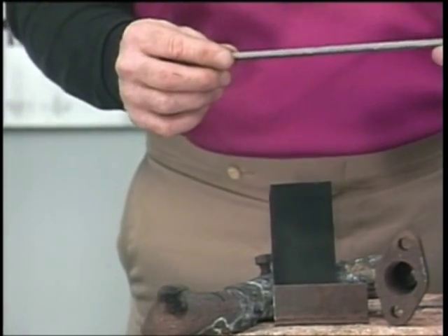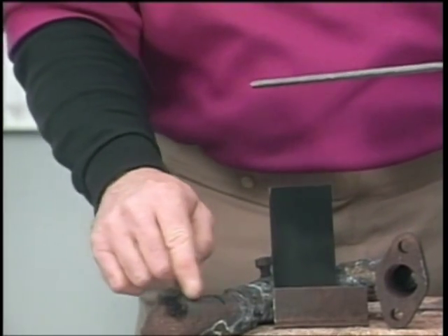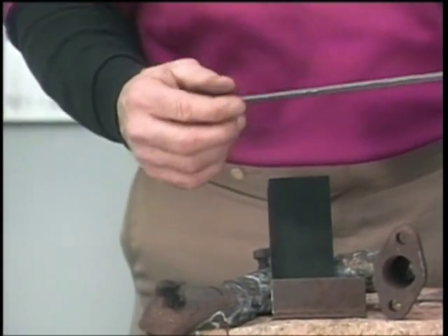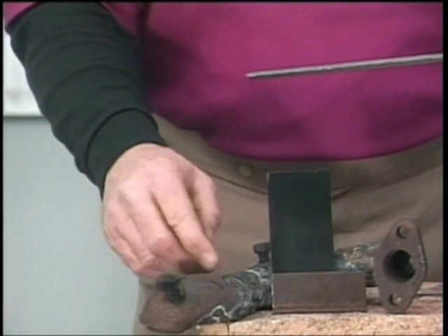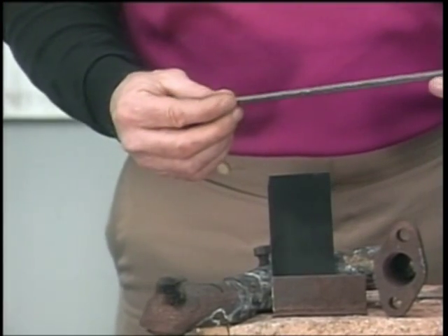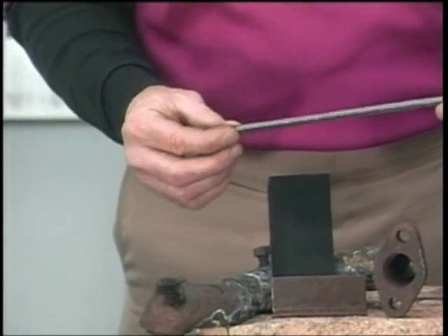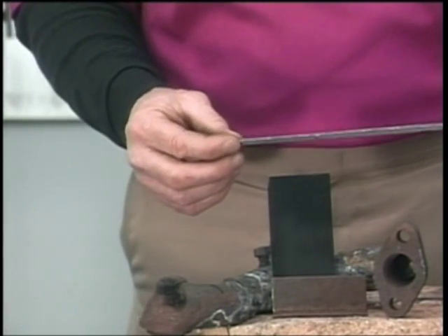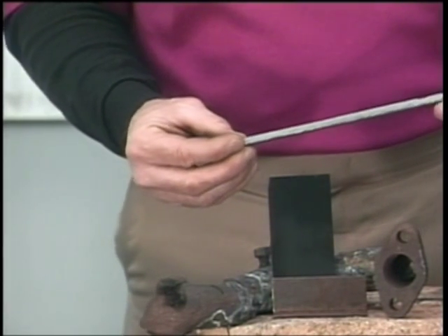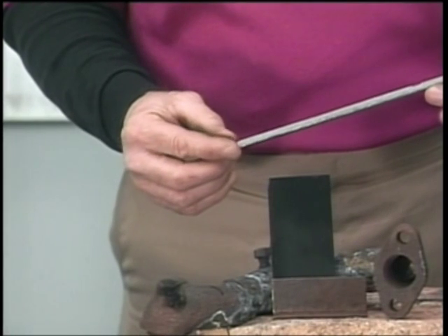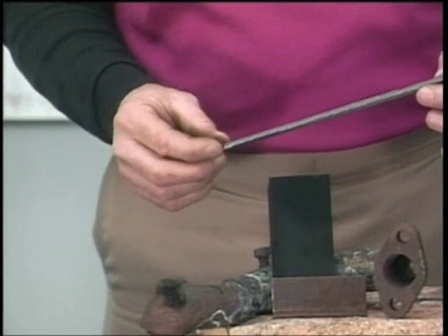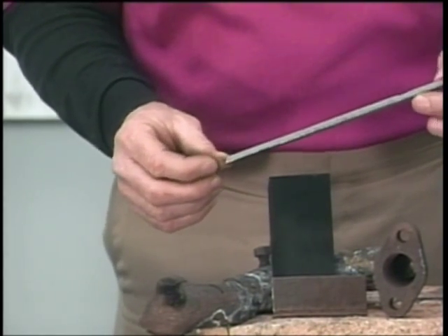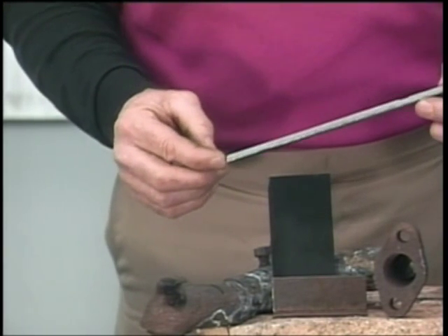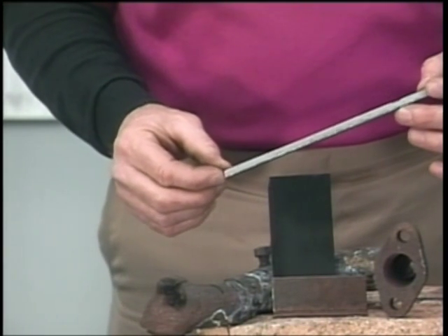Now, we've been able to have some real good results even on a lot of the older casts. This is just an old manifold right here off of an antique car. It's real low. The more carbon, the harder it is to weld. But with our gun, we've had some real good results going to a lot of antique tractor shows and also a lot of your hit and miss engine shows. Been able to weld up a lot of that old difficult cast that your regular conventional torches and electric welders have been having trouble welding. Now we can weld from very thin cast all the way up to 1-inch plate.